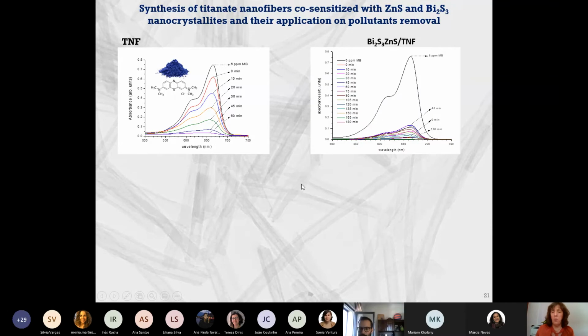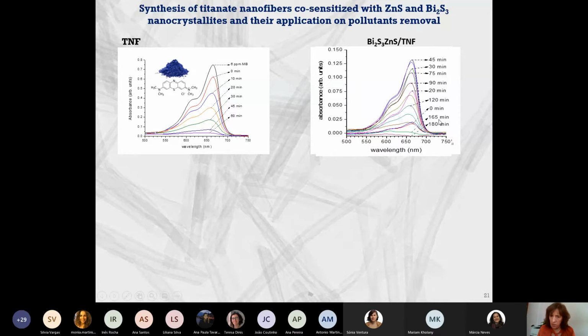However, when we start to use the nanocomposite with bismuth sulfide and zinc sulfide, this is our stock solution, and of course we have a dark period to allow the adsorption. After that, this is time 0 when I turn on the lamp. So if we look closer, where is the 0? It is here, okay? I turn on the lamp, and this is 20, 30, 45, and then I start to decrease.